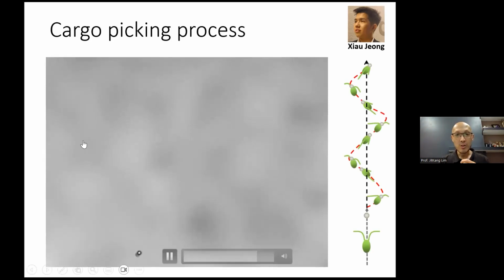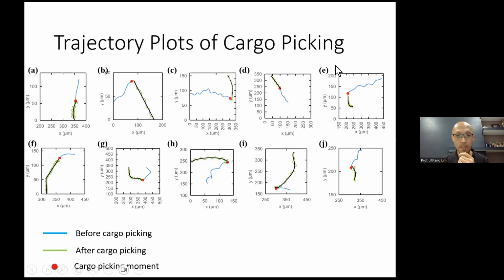So this video is captured by one of my students, Xiau Jeong, and we managed to capture about 10 pairs of this interaction where the blue line indicates before the cargo picking and the green line indicates after the cargo picking, where the red dot actually indicates where the cargo picking actually happens. And you could see in all cases, right? The cell, when it's cell alone, without having any cargo, without having any substrate, the cell actually moves quite linearly. And once it picks up the cargo, what really happens is it starts to undergo helical motion, right, in all conditions, in all 10 of the experiments.